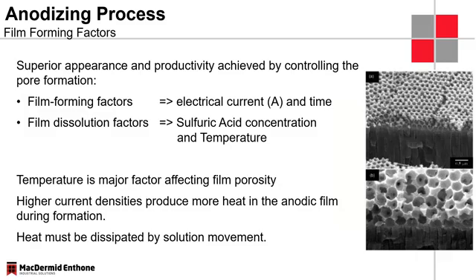So if we choose higher sulfuric acid concentration to get a better conductivity, at the same time we will also increase the dissolution or the redissolution of the anodized layer. And the same goes for the temperature. This is why temperature is a very critical parameter and factor when we anodize. Any higher temperature will start redissolving the anodized layer at a very high rate, and that's why it is extremely important to control that one parameter here in our anodizing tank.